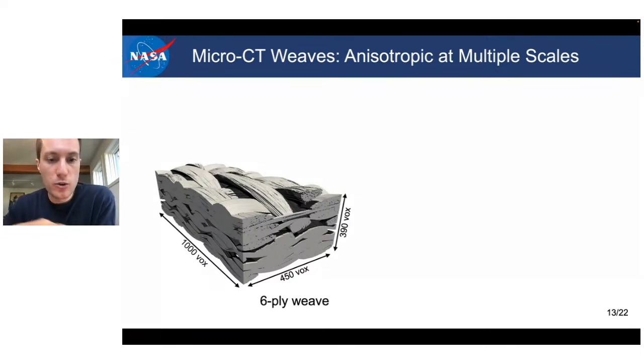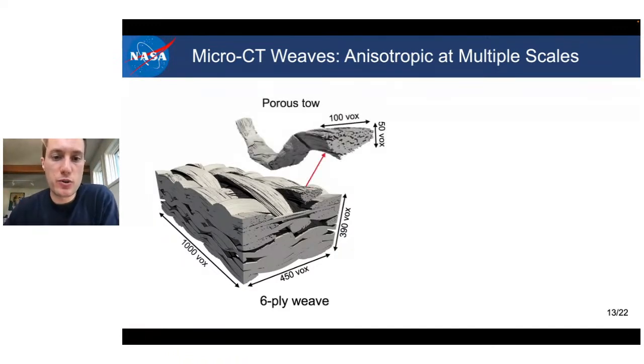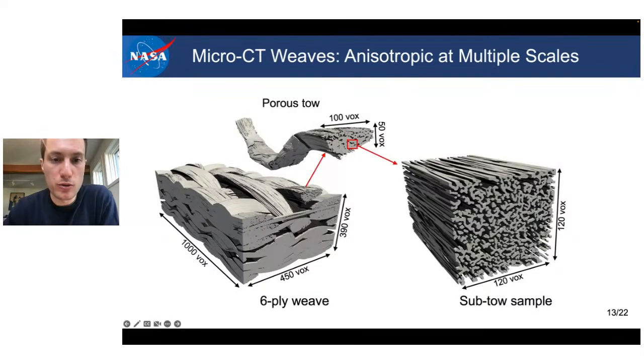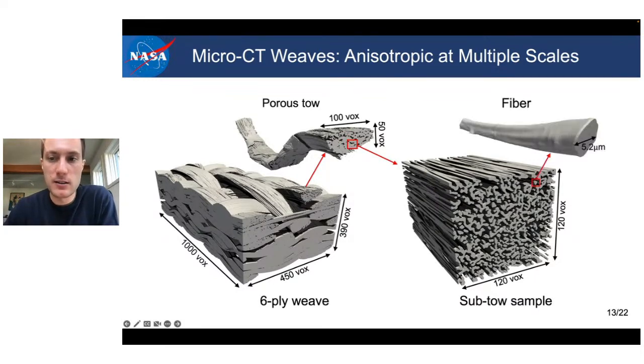And as you can see, the toes have a very directional pattern. And so this directional pattern influences, of course, the properties, meaning that in the warp direction, the properties are different than the weft direction than through thickness. And if we zoom into a subsample toe, we can see that there is porosity going throughout the toes, and this porosity also varies inside the toe, and this also affects the local properties and the anisotropy of